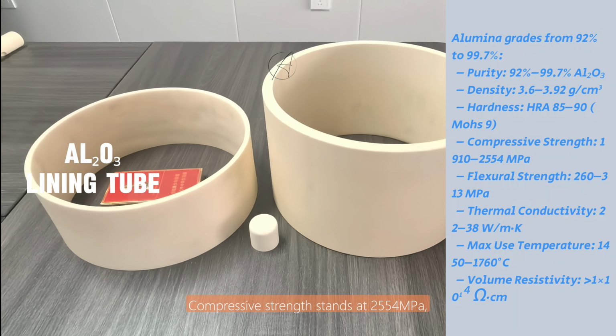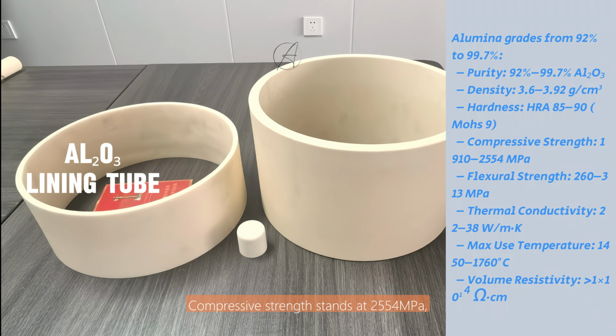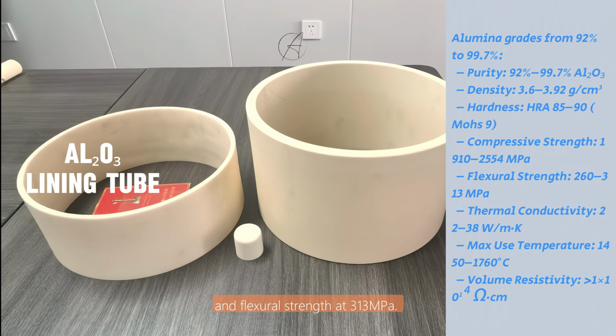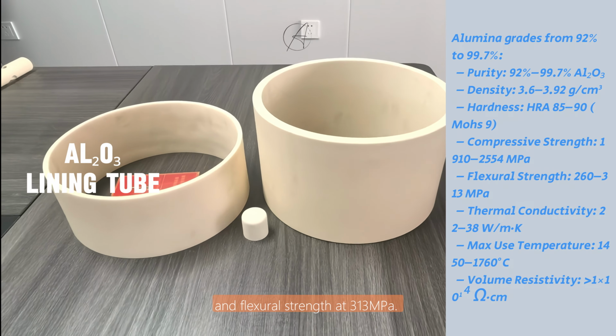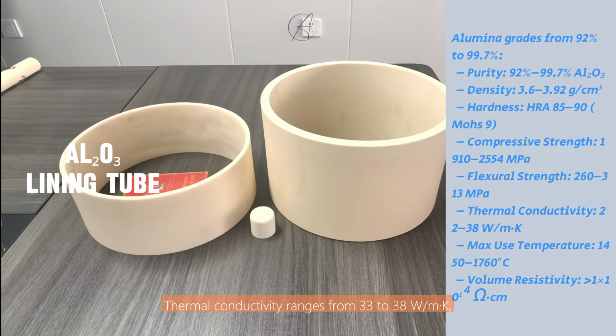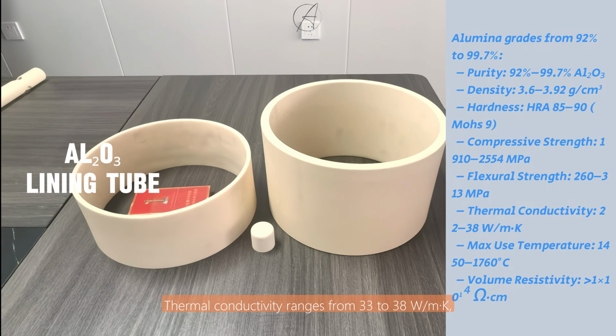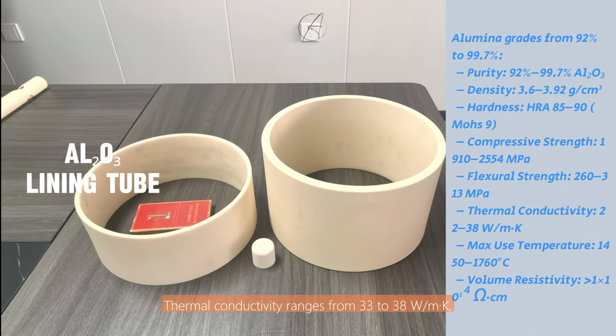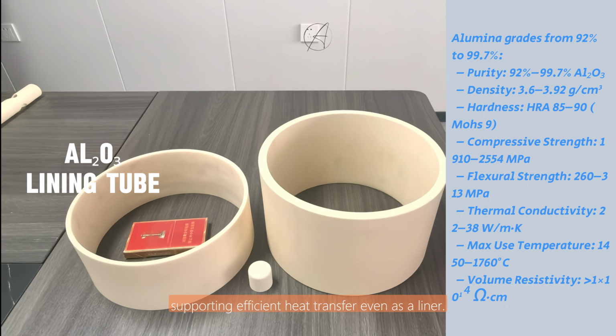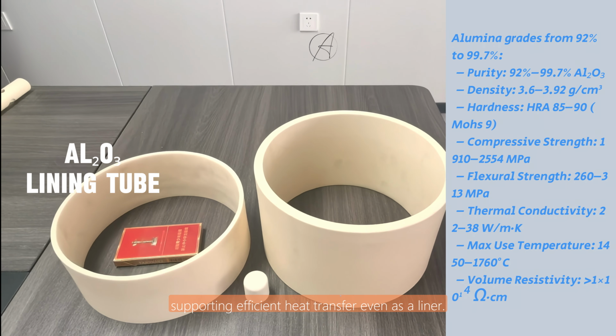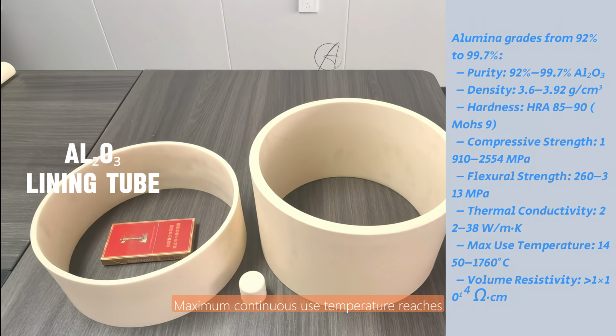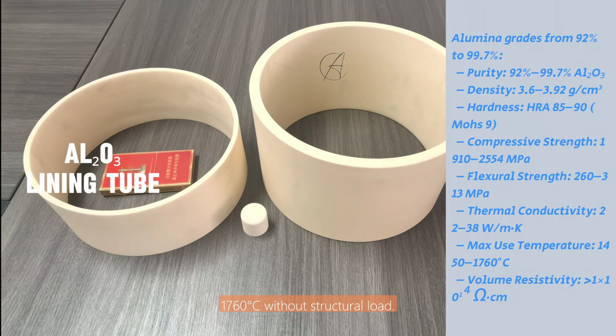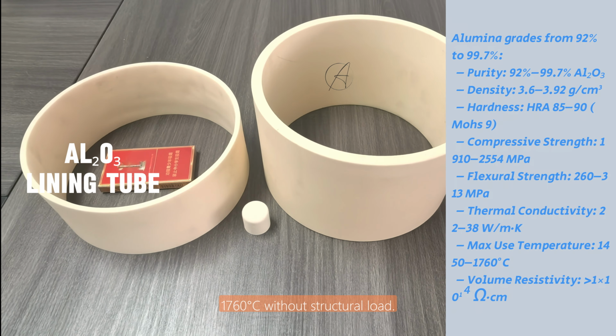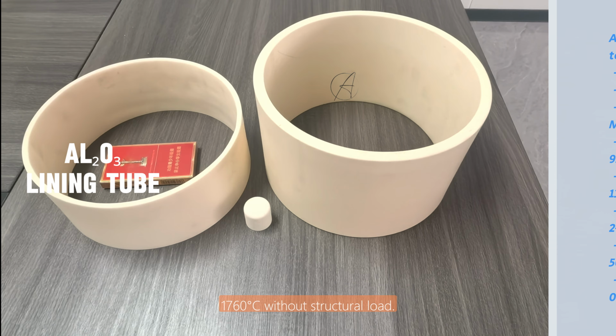Compressive strength stands at 2,554 megapascals, and flexural strength at 313 megapascals. Thermal conductivity ranges from 33 to 38 watts per meter Kelvin, supporting efficient heat transfer even as a liner. Maximum continuous use temperature reaches 1,760 degrees Celsius without structural load.